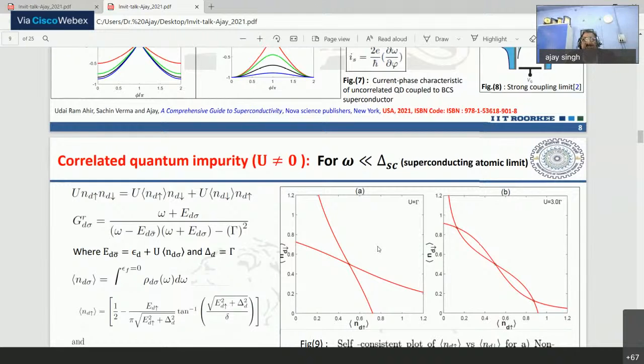We have found a result which shows the occupancy on the dot. If you calculate the particle solutions, which basically can be different physical states, and started when the energy omega is very, very small compared to the superconducting order parameter, a singlet doublet transition, which we have calculated for a superconducting system.